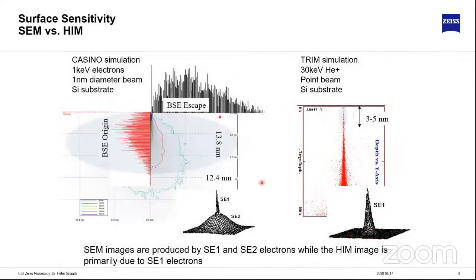Okay. I also told you we have a very good surface sensitivity, and I'd like to show you a little bit the difference. What is the difference between imaging with electrons on the left-hand side and imaging with ions on the right-hand side? If we want to image a sample at high resolution in an electron microscope, what we normally do is we image with secondary electrons. Okay, so what happens is the electron beam hits the sample. On impact, it will generate a secondary electron. That's called the SE1 electron, and that actually carries all the information about the sample, about the beam surface interaction.